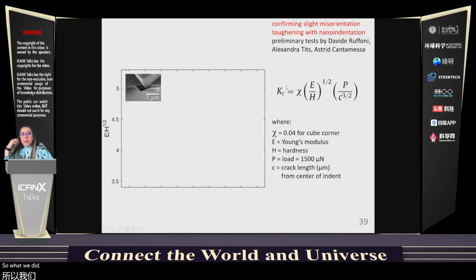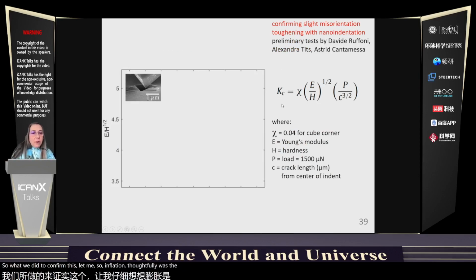So what we did to confirm this slight misorientation toughening was the measurement, or rather what we would like to do is to measure Kc, which is the fracture toughness. That's a numeric parameter, and then the Young's modulus divided by the hardness of the material to the 1/2 power, multiplied by the load that's applied by the indenter, and we use a cube corner as an indenter, and then measure the length of the cracks that propagate from the corners of that hole that the indenter makes in the material. And C is the crack length measured from the very center of the hole, of the tip, if you wish, and the tip of the crack.